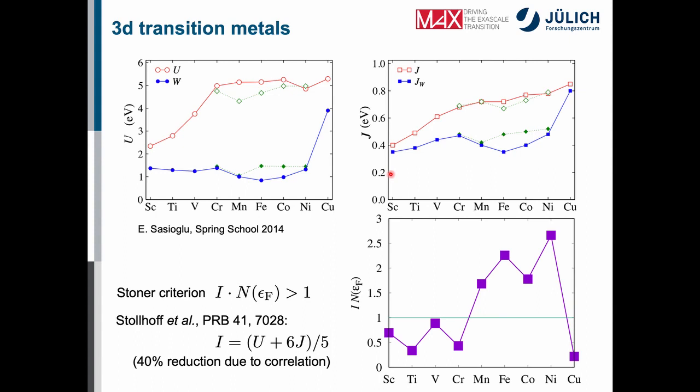As you know, some of the materials are ferromagnetic: iron, cobalt, and nickel. Also, manganese is ferromagnetic in the structure we have calculated it, a high-temperature phase, with 1 atom per unit cell. There is a criterion for ferromagnetism that can be derived using the Hartree-Fock approximation for the one-band Hubbard model. This so-called Stoner criterion states that if the product of Stoner parameter I and density of states n at the Fermi energy is larger than 1, one would expect the system to be ferromagnetic.